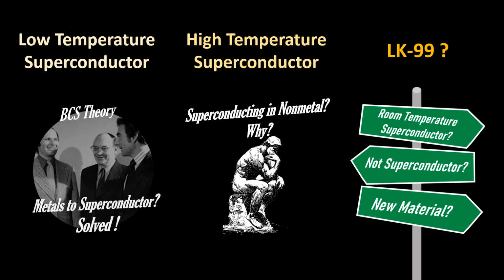However, based on the content of the papers released so far, it is highly likely that LK-99 is not a superconductor. The emergence of the Meissner effect by non-metal to superconducting state transition at the critical temperature, zero electrical resistance, and complete superconducting magnetic levitation due to flux pinning, these three factors that should generally be satisfied if it is a superconductor have not been confirmed. While magnetic levitation is indeed a representative phenomenon observable in superconductors, the presence or absence of magnetic levitation does not determine the existence of the superconducting phenomenon.